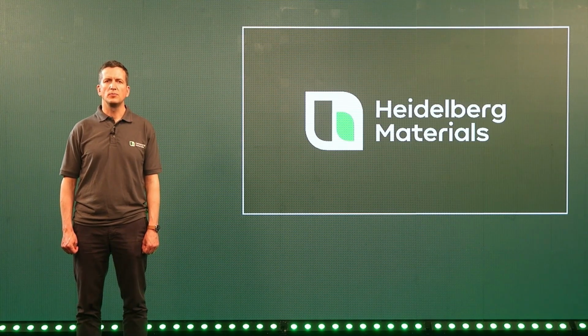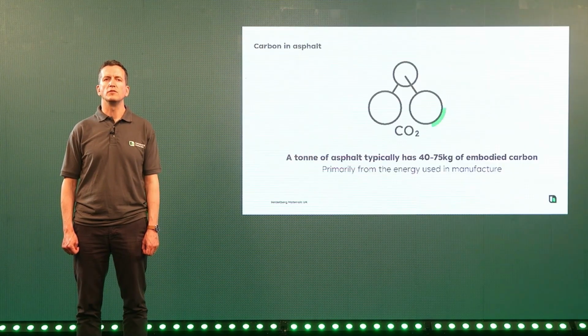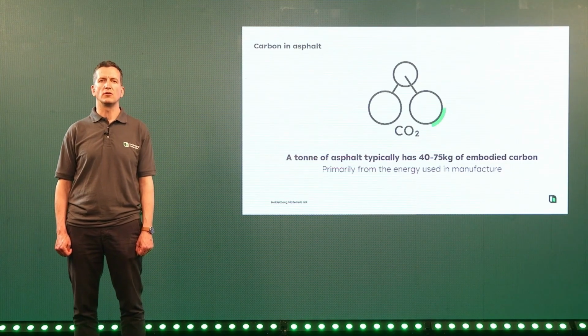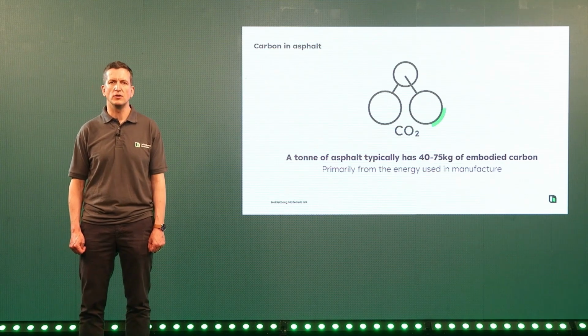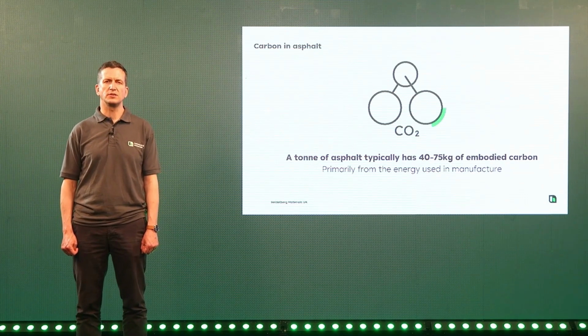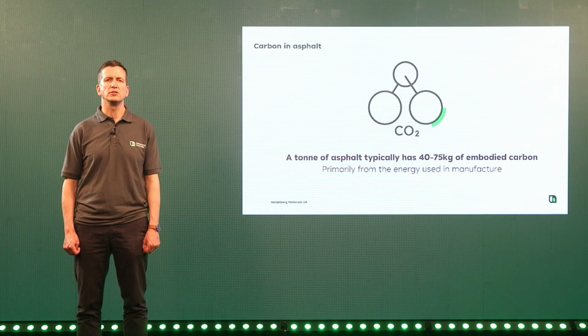The embodied carbon per tonne of asphalt is typically between 40 and 75 kilograms, depending upon the type of asphalt, raw materials, transportation, and production processes used. Of these, emissions from the energy used in production and the raw materials used are by far the largest contributors, with emissions associated with the laying of the asphalt only around 4 to 6% of the total embodied carbon of